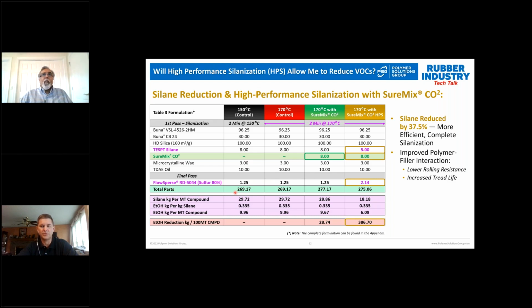So what you'll see is a typical recommendation of 8 parts of silane per 100 parts of silica, and that was based on what properties could be developed during mixing within a mixed cycle where you could get a compound that was processable, right? So that was the box that was being worked inside of. What we looked at, as we were considering the dramatic processability improvements that we get with SureMix, was there an opportunity for 2 things?